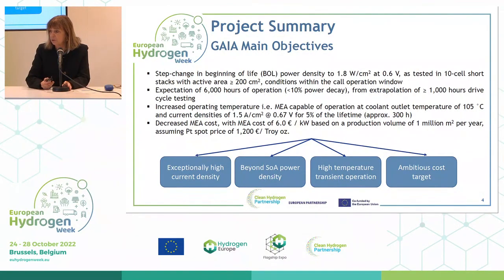And then, as always, reducing the amount of platinum and reducing the cost. So if we bring all of that together, then it's an exceptionally high current density, 1.5 amps per square centimetre, beyond state-of-the-art power density, 1.8 watts per square centimetre. We've got this high temperature transient operation and a very ambitious cost target. So the call text specified €6 per kilowatt.